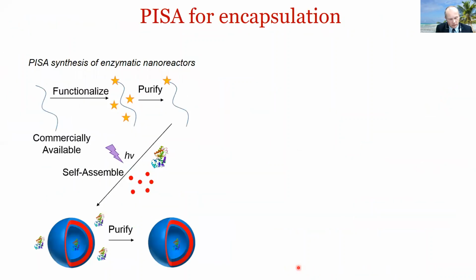But one of the things PISA is also interesting for is encapsulation. So as you imagine, if you start with, for example, a commercially available polymer such as a PEG, you functionalize it with whatever initiating group you want to use to form your second block. You can purify it, and then in one step you can perform the polymerization in the presence of something that you'd like to encapsulate, in this case just shown as an enzyme, and potentially use photo initiated systems, which, as I said, are very mild, so it doesn't damage delicate enzymes, etc. You can then do the chain extension or self-assemble in one pot, and then just purify to be able to access encapsulated species within the constructs that you're making, in this case targeting vesicles.